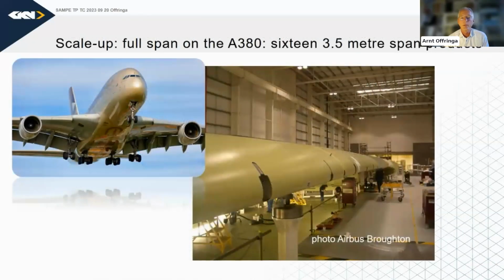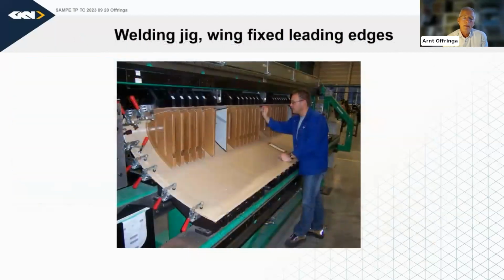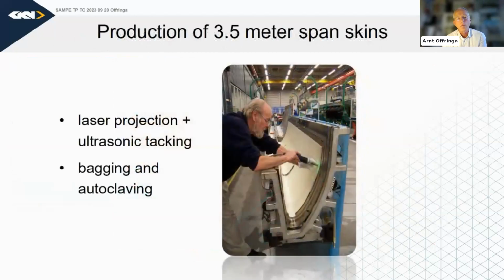And here we see the A380, which also has this same product at a much larger scale. These products have a length of approximately 3.5 meters and a height of about 1 meter. The welding is highly automated, so that's resistance welding. But the skins are autoclaved, so fairly traditional.